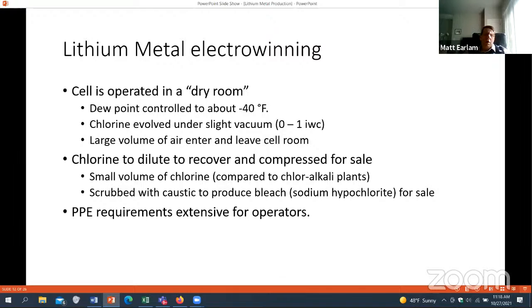The cells are pretty small, so there's no real value in compressing the chlorine for sale, because you're not really generating a lot of chlorine compared to a chlor-alkali plant. So it's not done. What they actually do is scrub the chlorine that comes off, diluted with air, with sodium hydroxide to produce bleach. And then the bleach material, which is sodium hypochlorite solution, is sold as a product. So there's no chlorine recycling in this process.